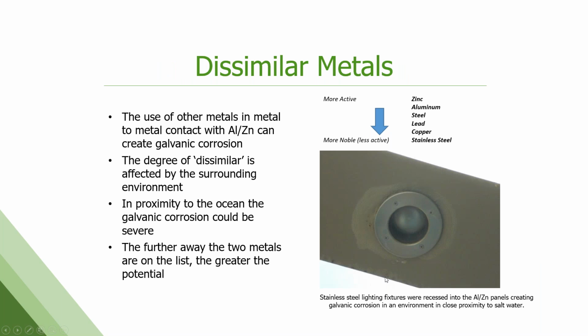This is when you use a dissimilar metal. So we have the galvanic scale here. The further apart items are on this scale, the more reactive they're going to be in a corrosive environment. And again, the corrosive environment is important. So this is mostly in marine settings that we see this happen. So say you have a galvalume panel with stainless steel, which is what we have here. These are stainless steel light fixtures that were recessed into a zinc aluminum painted panel. This house was 200 feet off the surf break in Carlsbad, California. And within a year, we had this corrosion developing on the zinc aluminum panel because it's sacrificing itself to protect the stainless steel.